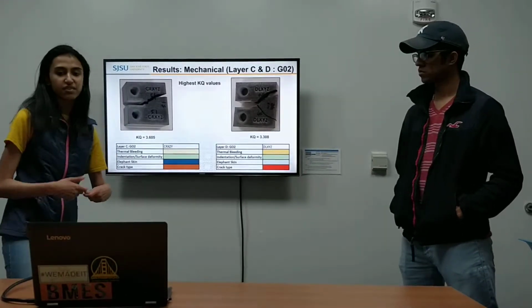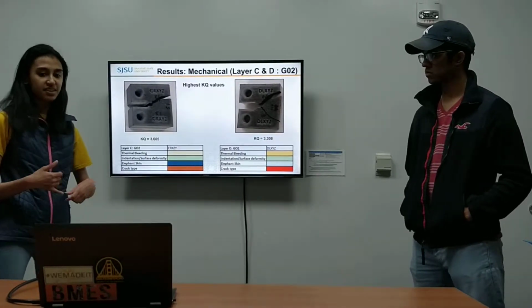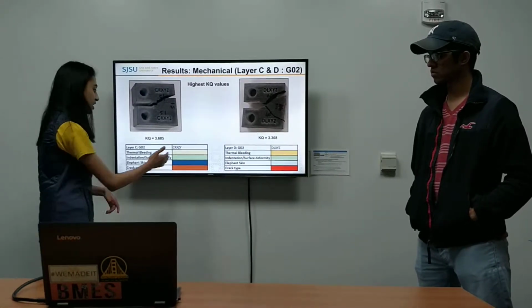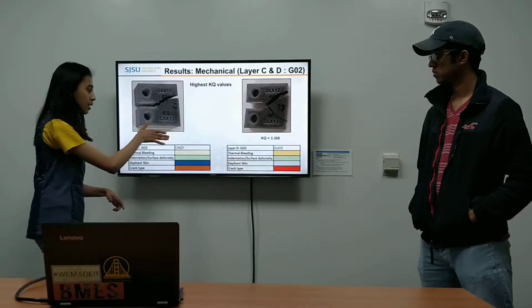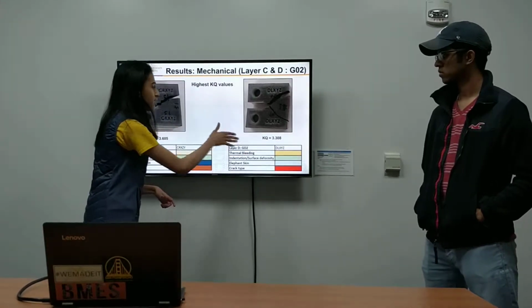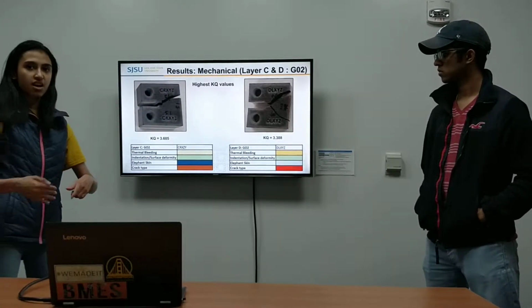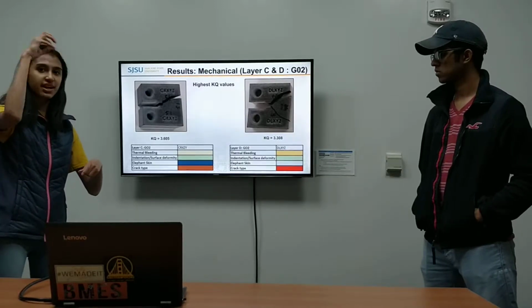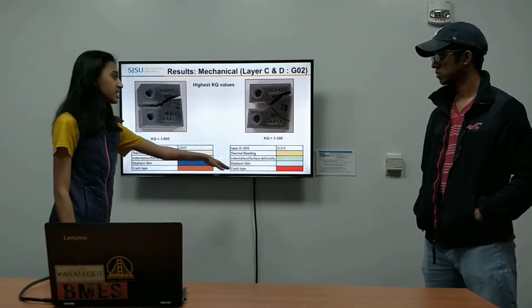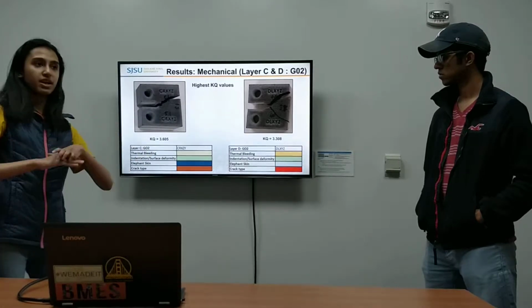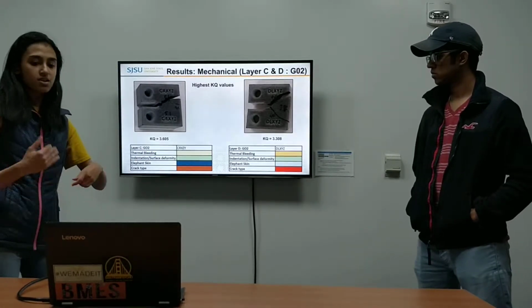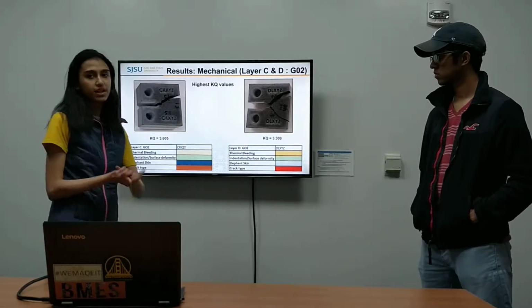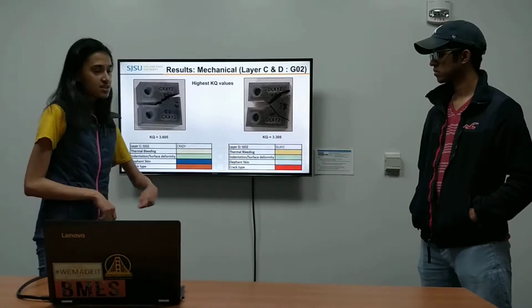Moving on with the results for the C and D layers, you can see it's the same way: thermal bleeding is less for the C layer compared to the D layer, because the C layer was the top layer and it was exposed directly to the printhead, but the D layer was the layer laid down on the print bed, so it had more thermal bleeding compared to the C layer.